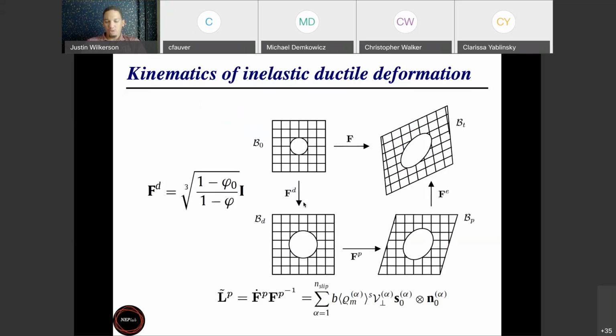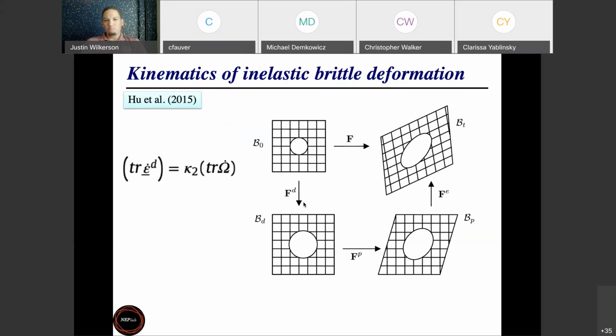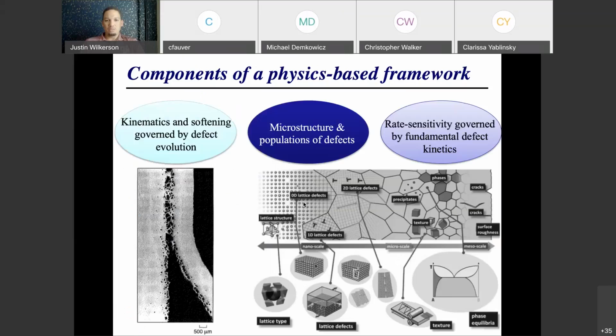Okay, so I won't go through that any more than to say that this is what we use for the kinematics for porosity. So you have this isotropic damage tensor that's created, and then for a brittle material, it ends up becoming an anisotropic damage tensor. And then a brittle material can still have lattice slip type plasticity as well, if you want to account for that.